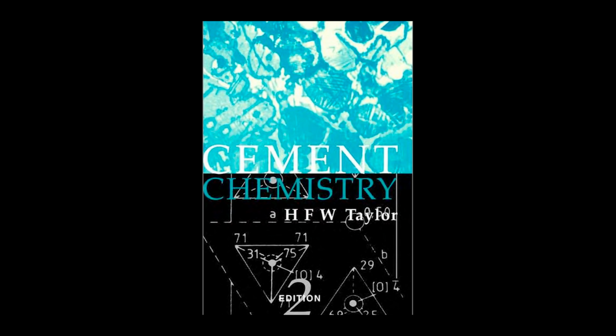This hemihydrate then converts back into gypsum when it meets water, creating these fine secondary gypsum crystals that interlock and cause the rapid stiffening. But since no real chemical damage has occurred, remixing just breaks the crystal linkages and the concrete is fine.